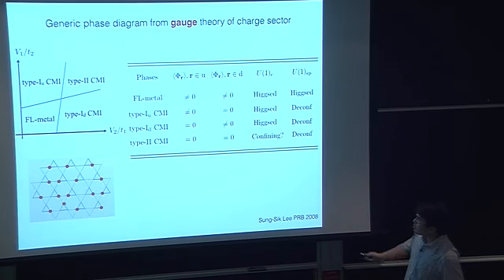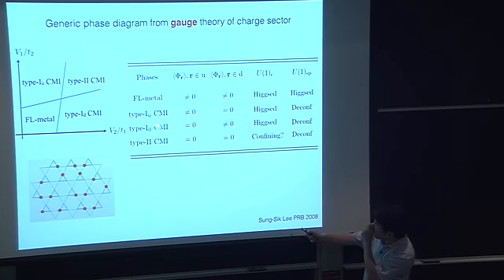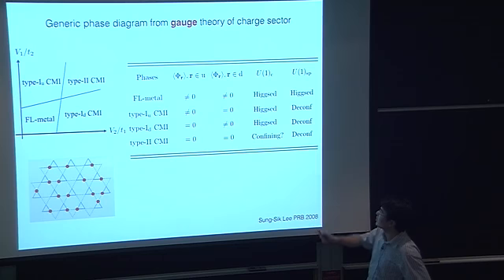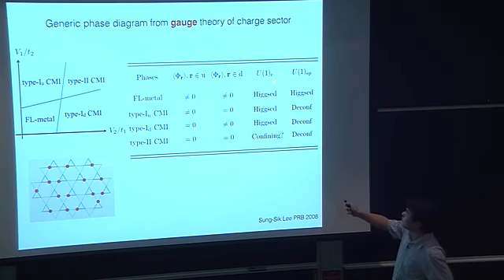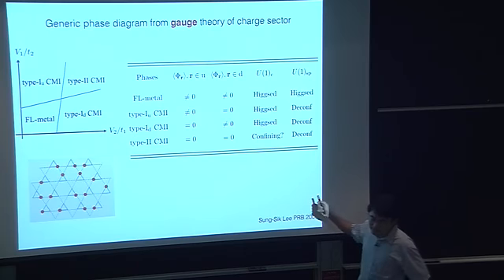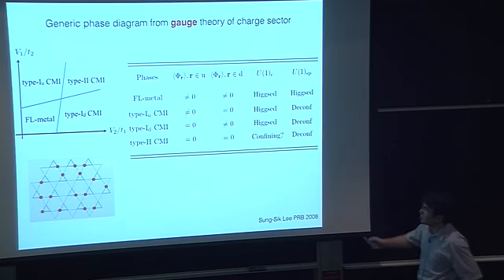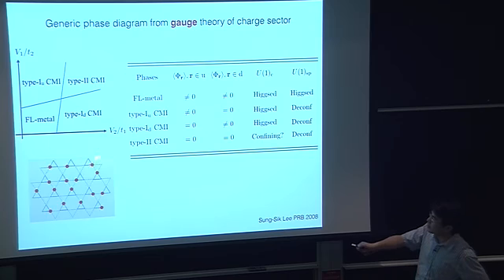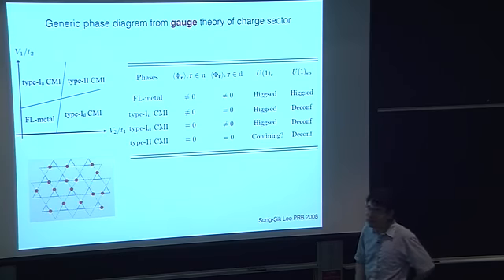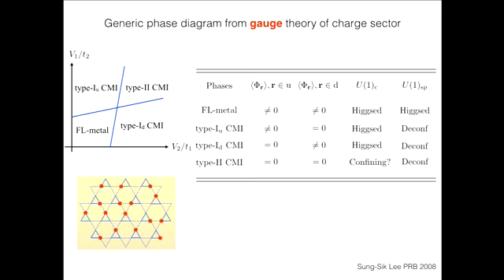In a type 1 cluster Mott insulator, the electron number on the down triangle is strongly fluctuating, but the electron density on the up triangle is fixed. So the charge boson on the down triangle is condensed, but the charge boson on the up triangle is not condensed. Because the charge boson is condensed, the U(1) charge gauge field is Higgsed, but the U(1) spinon gauge field is not Higgsed; it's deconfined because of the presence of the spinon Fermi surface. Similarly for the type 1 down cluster Mott insulator. In the type 2 cluster Mott insulator, both the up and down triangle electron densities are fixed to be 1. So neither charge boson is condensed. But the U(1) gauge field that causes spin-charge separation is still deconfined because of the spinon Fermi surface.